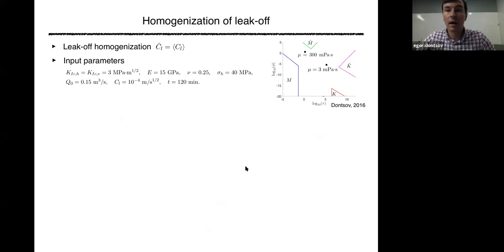Finally, the last is leak-off, right? Your hydraulic fracture simulator depends on elastic properties, toughness, stress, and leak-off. This is the last part. So what do we do? First of all, we need to test cases which are close to the leak-off dominated regime, because otherwise we won't be able to see any effect. That's why we selected these properties with a high value of leak-off.